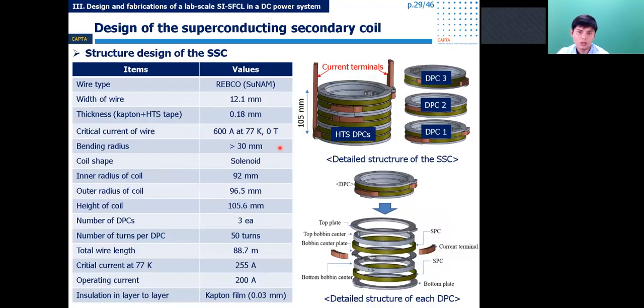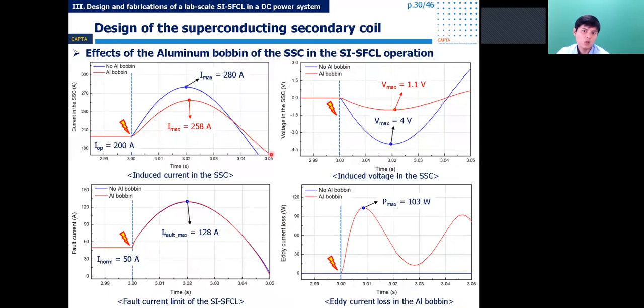And this slide shows the detailed design specification and structure of the secondary coil. A circular shape double pancake coil was applied. There are 3 DPCs with 50 turns each DPC. It is wound on the aluminum bobbin. So the question is why we use the aluminum bobbin in the secondary coil. The reason is that the aluminum bobbin, like a single turn coil, separates the secondary coil from the magnetic change in the iron core during the transient fault. Thereby, it can reduce the induced current and the induced voltage in the secondary coil.